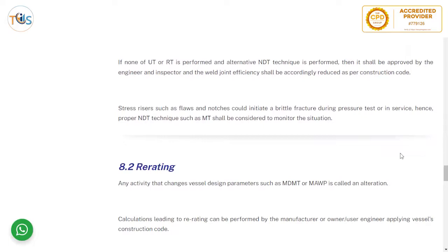For example, if you cannot do RT, then they can ask for a deviation, asking to do UT instead for some reason, for safety reasons. So you still have, because both are volumetric, a joint efficiency of 1. Now, if you cannot do any one of them for any reason, such as access or it's not practical, and you do some other tests like, say, MT or PT, now the joint efficiency is normally 0.85. Then you don't do volumetric, you do surface examination by MT or PT, for example. So the joint efficiency should be reduced accordingly as per the construction code.